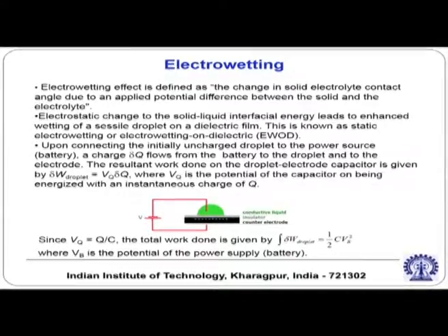So if you look at this system, you have a counter electrode on which there is an insulator. Typically we often just draw the insulator but not the hydrophobic layer. If the insulator itself is a good hydrophobic layer, maybe an additional hydrophobic layer is not necessary. But if there is no hydrophobic layer and the insulator itself is not sufficiently hydrophobic, then it will not form the droplet on the top of that; we have to keep that in mind.